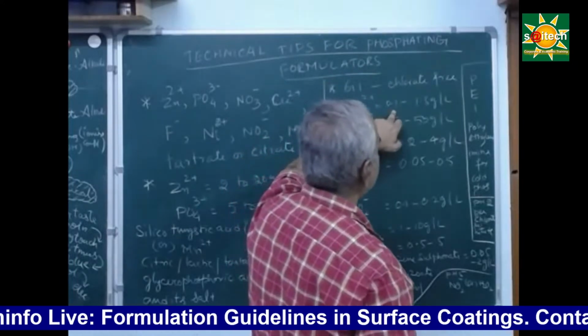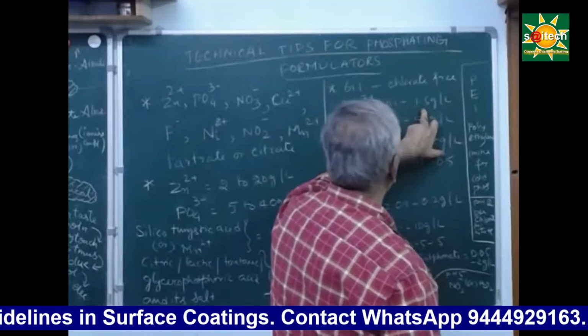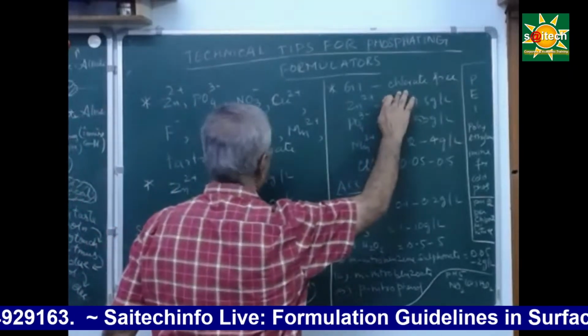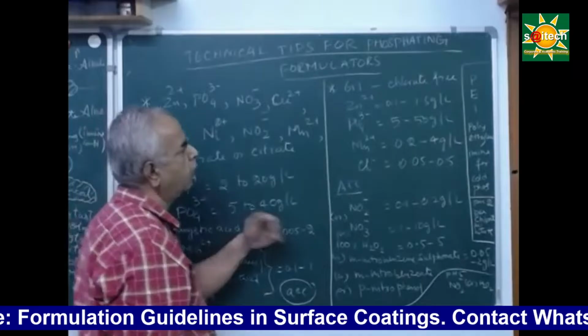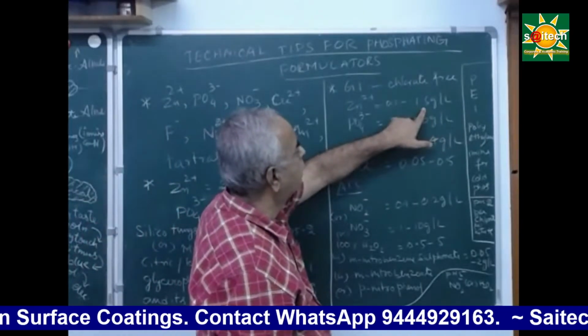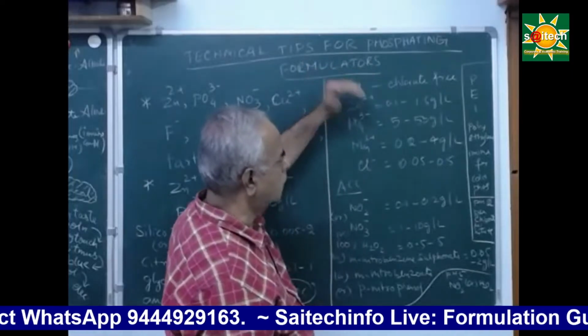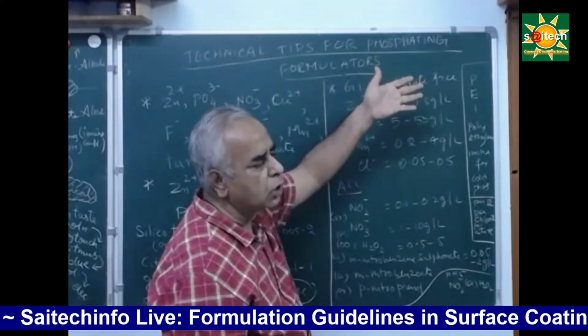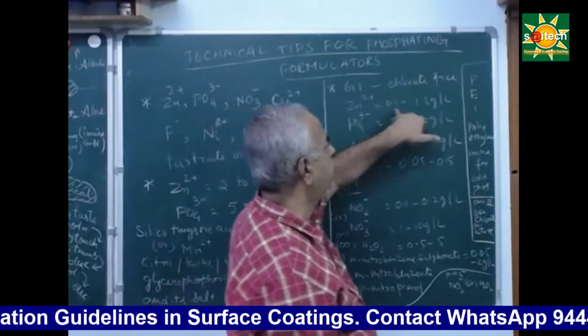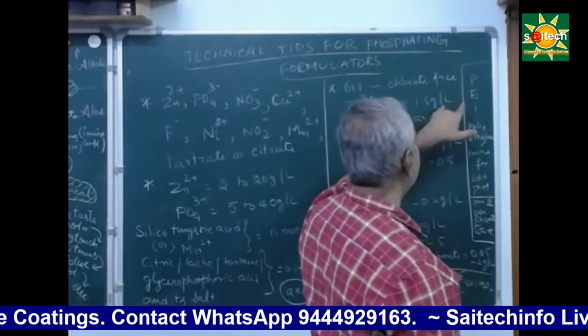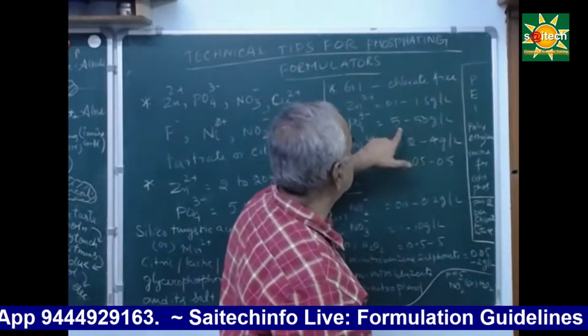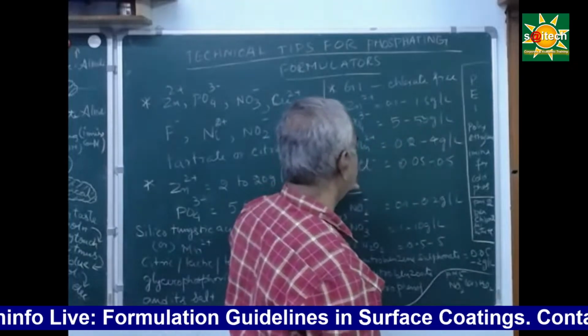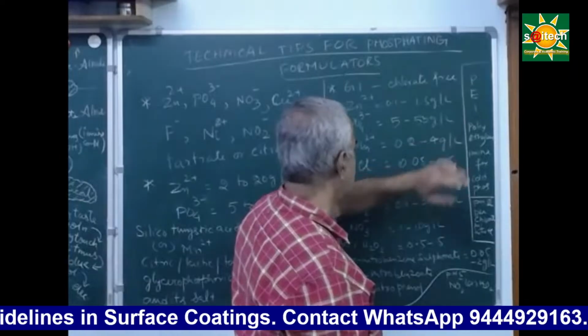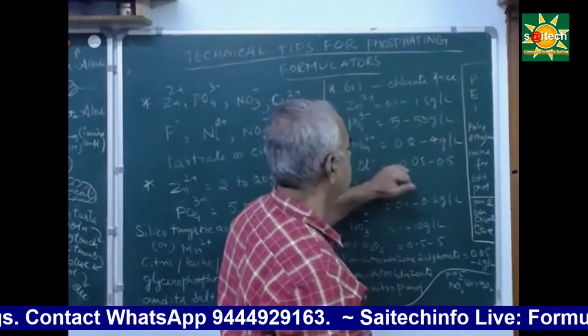Here we have zinc 2 plus and the load is 0.1 to 1.5 gram only. So you can find the difference between mild steel and galvanized iron. Here we have 2 to 20 grams, whereas you cannot exceed 1.5 gram per liter as far as GI is concerned. The zinc load should be low because it's already galvanized, so you cannot load further. So zinc 2 plus should be between 0.1 to 1.5 gram per liter. Phosphate is 5 to 50 gram per liter, manganese 2 plus 0.2 to 4 gram per liter, and chloride ion can be 0.05 to 0.5.